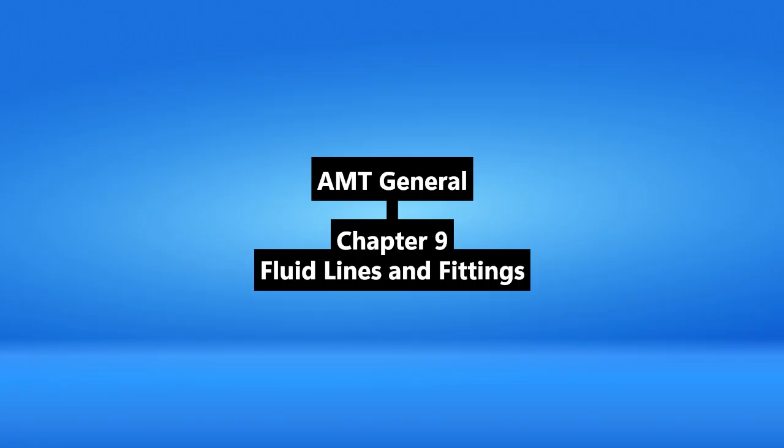Now let's move on to titanium. It's presented as the premium choice. It is, pretty much. Titanium 3AL-2.5V is used in high-performance aircraft hydraulic systems, typically above 1,500 psi. Because it's even stronger and lighter than steel. Exactly. Incredible strength-to-weight ratio. You'll often see Cryofit or swaged fittings used with it.